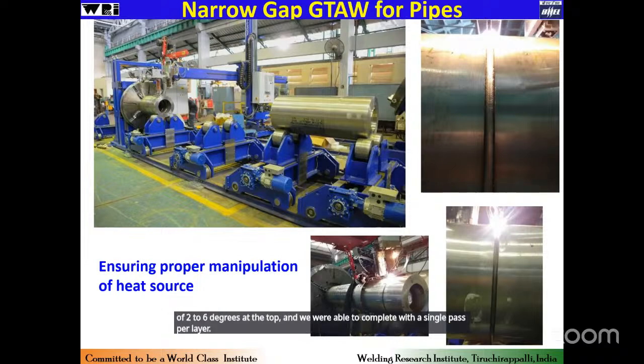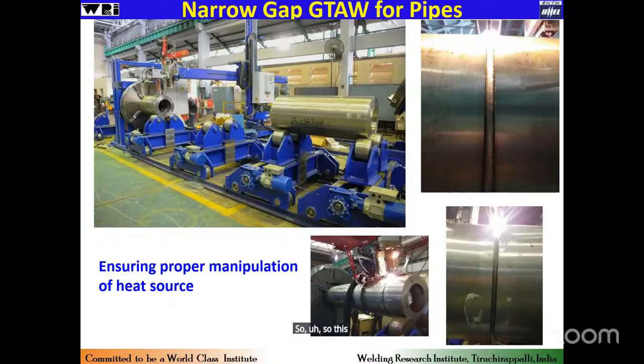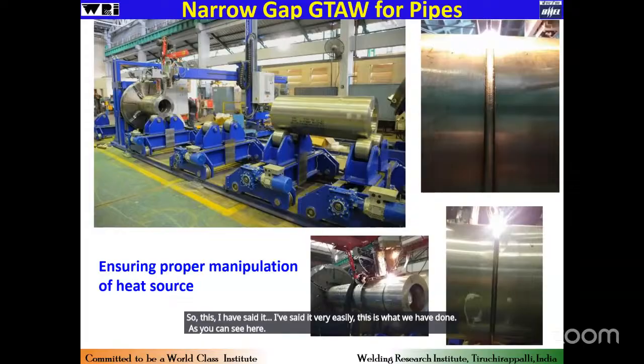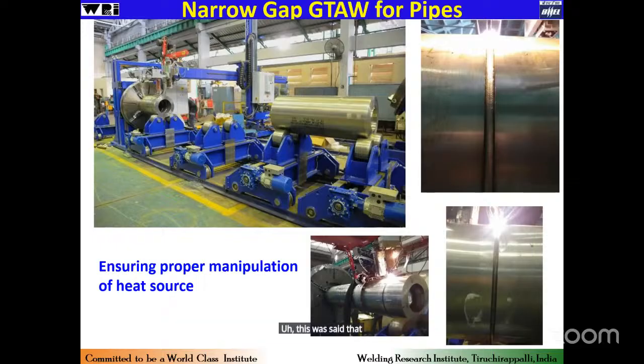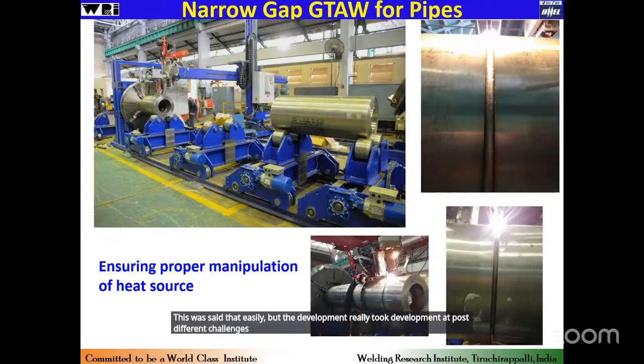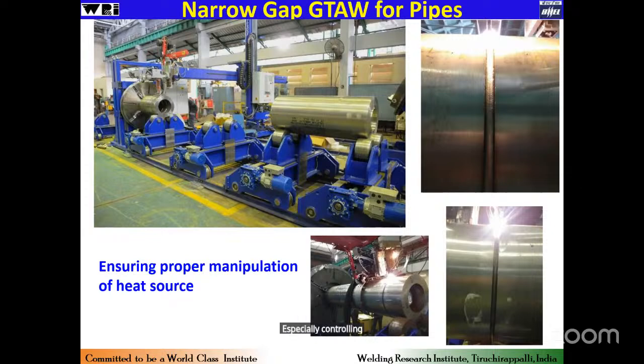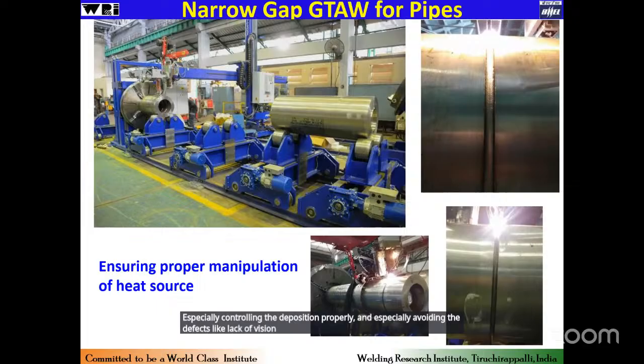I have said this very easily, but this is what we have done. As you can see here, we have done the optimization in 1G as well as in 5G. So 1G is where the pipe is rotated, and 5G is where the torch is rotated, in the narrow gap condition. It was said easily, but the development really posed different challenges for us, especially controlling the deposition properly and avoiding defects like lack of fusion. So we had to do proper optimization.